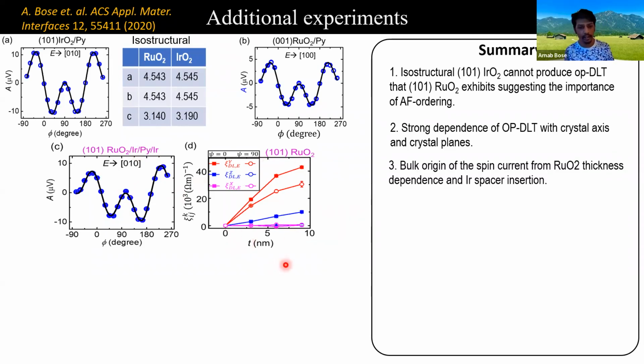The next thing that we did, we varied the thickness of the heavy metal, which is ruthenium dioxide here. And we find that as we increase the thickness of ruthenium dioxide, spin torque increases. And finally, it will saturate. Again, this suggests that the spin current that we report here originates from the bulk bands of the ruthenium dioxide.